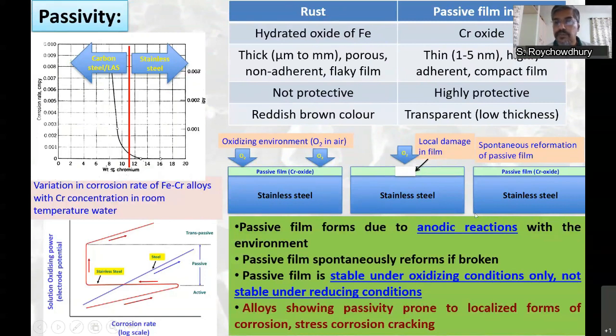The passive film forms due to anodic reaction, as I told you. And the beauty is that it spontaneously reforms. If it is broken due to scratching or handling, it reforms spontaneously. And you can realize that you need oxidizing conditions for this passive film to be stable. So such alloys work well under oxidizing conditions. Even though the corrosion is uniform, they have a different set of problems, which are localized forms of corrosion that we will see later on.